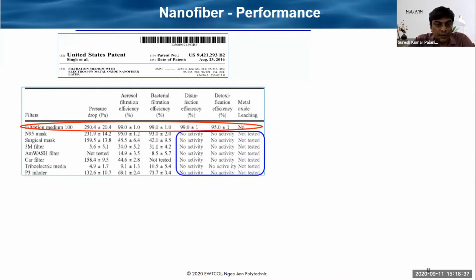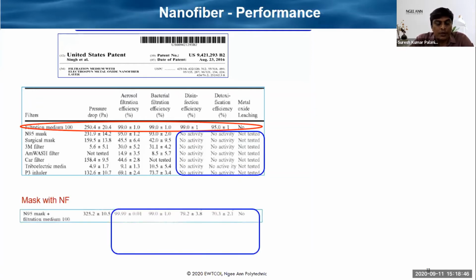This figure shows the existing masks and filters, where there is no disinfection and detoxification property. We also have the advantage that this nanofiber can be embedded in a mask, and we have tested with a commercial N95 mask with our nanofibers, which shows an improved aerosol filtration efficiency of more than 99.99%. We also added the other functionality of disinfection and detoxification. For this N95 mask, we observe an efficiency of 79% for disinfection, whereas detoxification is around 70%.